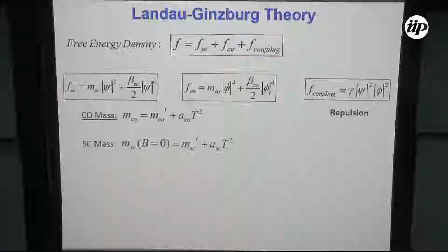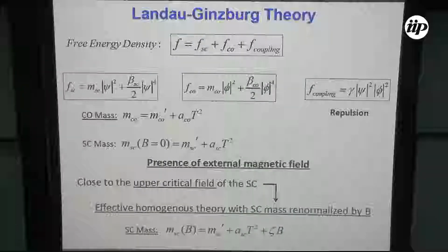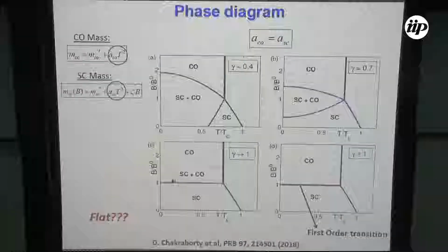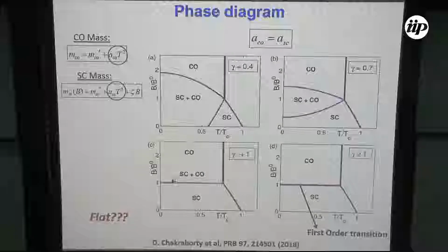If we put magnetic field, what happens is that close to the upper critical field, we can treat the problem as an effective homogeneous theory, but with the superconducting mass being renormalized by magnetic field. So the superconducting mass will behave linearly in magnetic field close to the upper critical field. With this parameterization, let's plot the phase diagram in the BT plane. So if we look at the BT phase diagram, magnetic field temperature phase diagram, for not strong coupling, that means if the two fields are not strongly coupled with each other.